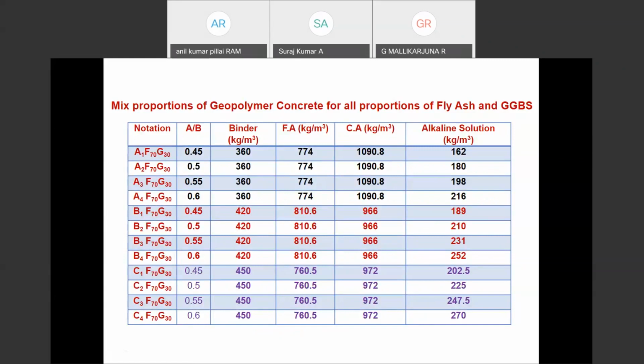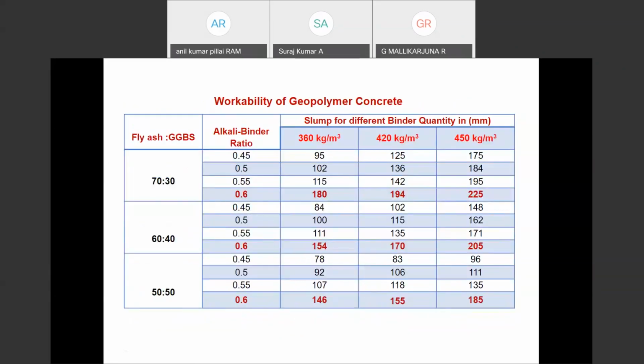For all the mixes we considered these quantities, and here, regarding the workability of the concrete, whenever we go for a higher alkaline to binder ratio, we observed more workability at 60-40 and 50-50. If you observe, the main thing is that whenever we increased the GGBS content, automatically the workability is reduced. Those things we observed from this experimental program.